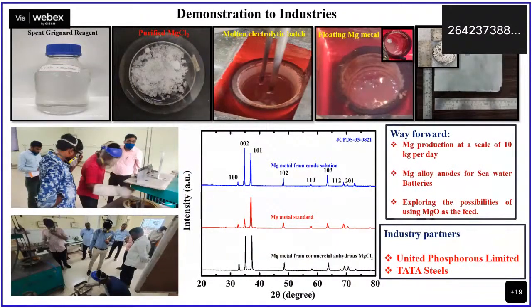We have demonstrated this to various industries. We demonstrated it to Tata Chemicals, we demonstrated the setup to Tata Steel, and we demonstrated it to United Phosphorus Limited recently, where we could get 98.2% pure magnesium from the secondary source which they provided. And we are expecting a project from Tata Steel on the ferrochrome slag. They need to extract the magnesium which is available there in the form of magnesium chloride and then convert it to magnesium.